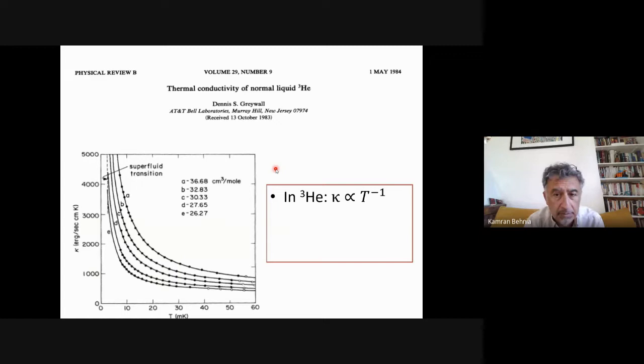Now, thermal conductivity of normal liquid helium-3 has been studied in detail, and what experimentalists found in agreement with theory is that thermal conductivity is proportional to the inverse of temperature. Now, for some reason which escapes me, nobody had paid attention that actually this kappa proportional to T^-1 is strictly equivalent to WT proportional to T squared, which is what we metal physicists are talking about.